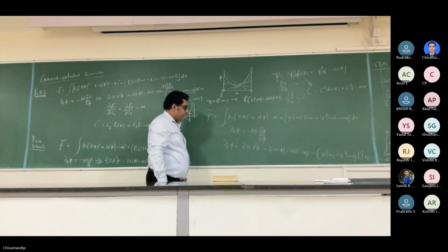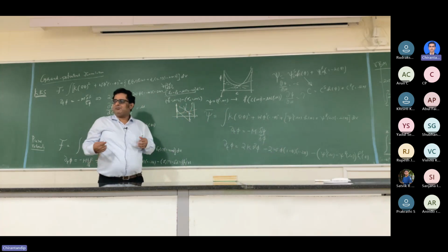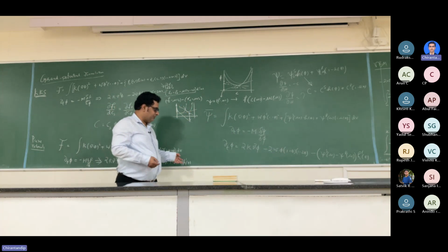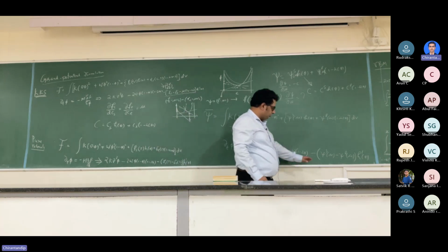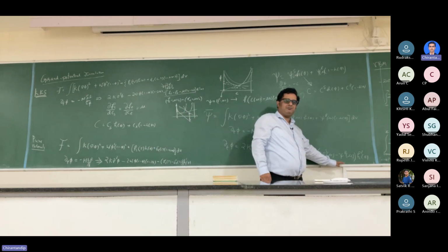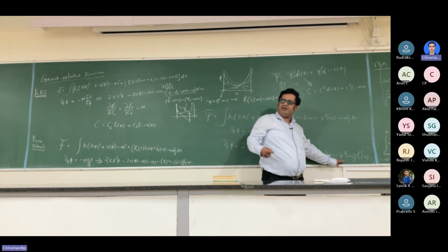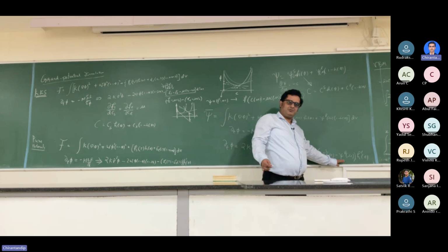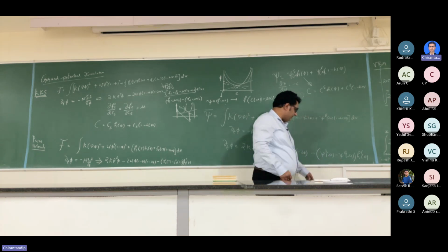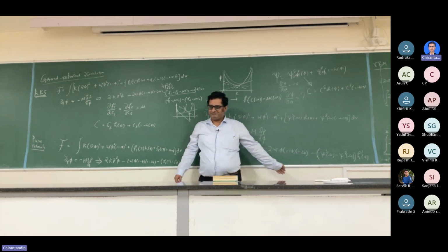Right? I mean, if you look from a thermodynamic point of view, all we did was go to asking the question, what is the thermodynamic driving force of the system, and construct a potential based on the thermodynamic driving force of the system. Okay? And thereby it comes out the same way the pure material things come out. So there also the starting point was asking what is the thermodynamic driving force of the system. Right? Not the effective energy of the system. Thermodynamic driving force. As you ask that question, this is the natural outcome.